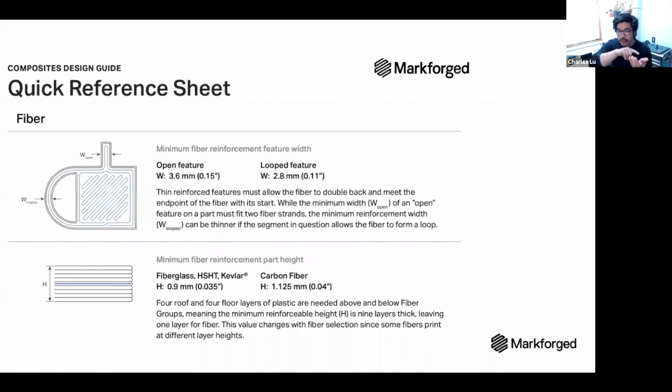Yeah, so a feature is open feature, 1 millimeter per pass. So you're actually getting 2 millimeters. And the walls are about 0.4. So if you go into Eiger and take a look, it's free to use and get in there and look at the internal view and stuff. Each of the fiber passes is 1 millimeter, and then each of the material pass is about 0.4. So you can sort of calculate that way.